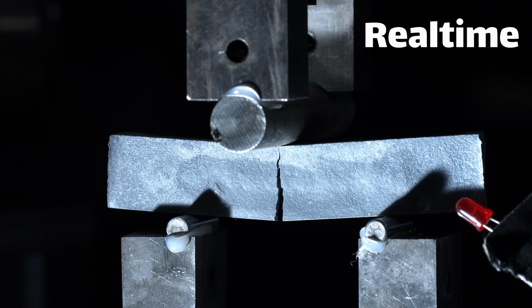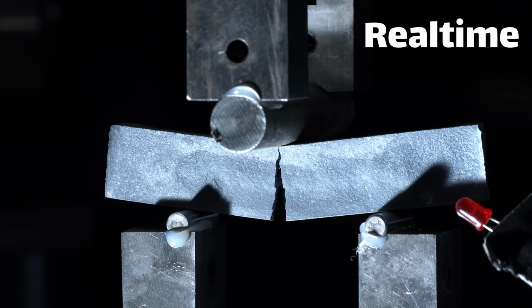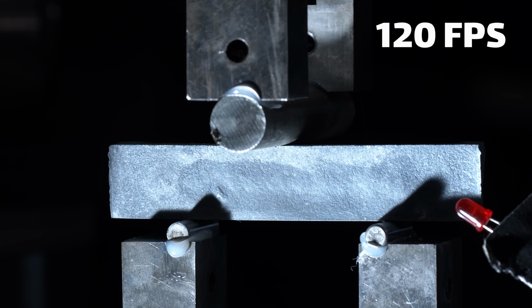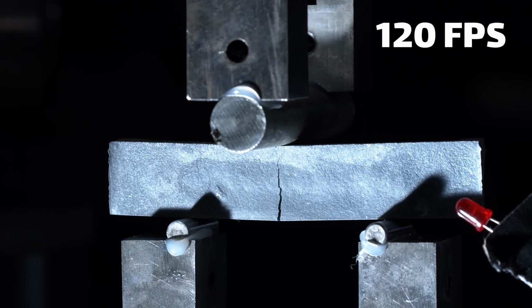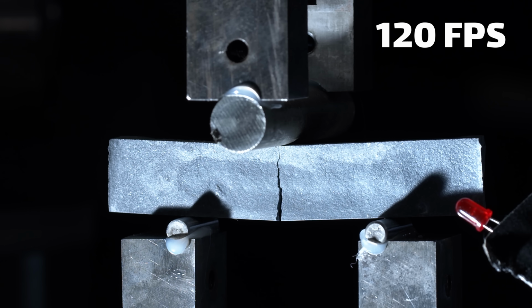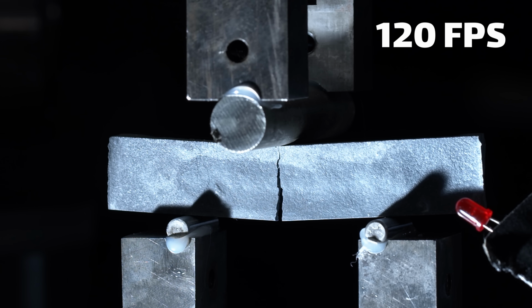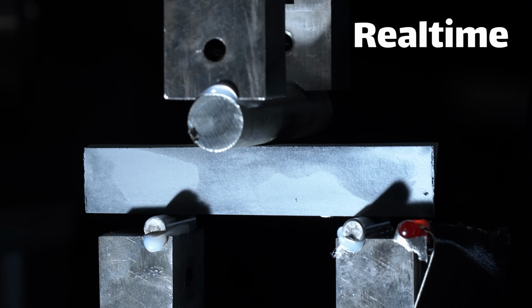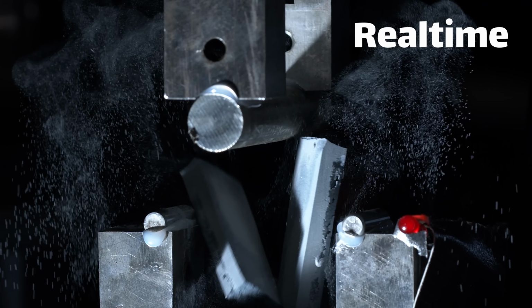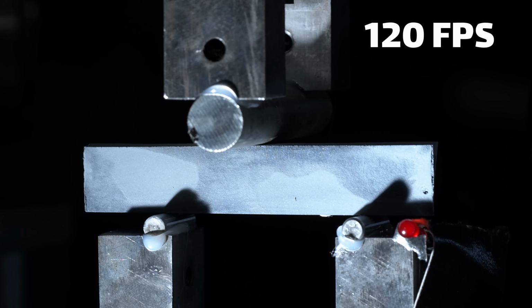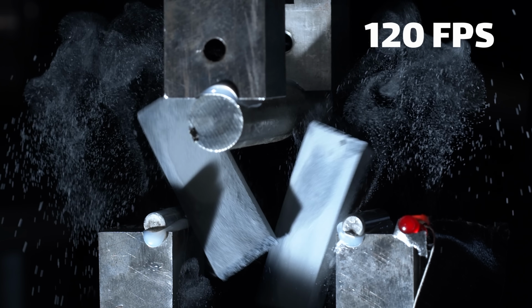The crack starts to slowly propagate its way up. It's not a brittle fracture at all. It's kind of just peeling apart, which absolutely makes sense. It's essentially silicon carbide held together by dried starch glue. But when we look at the fired piece, you can see that there's essentially no deformation while it's being compressed until it suddenly fractures in a very quick, brittle fracture event. And this is classic hallmark ceramic, where once a crack initiates, it propagates super rapidly, and then the whole thing is blown apart.